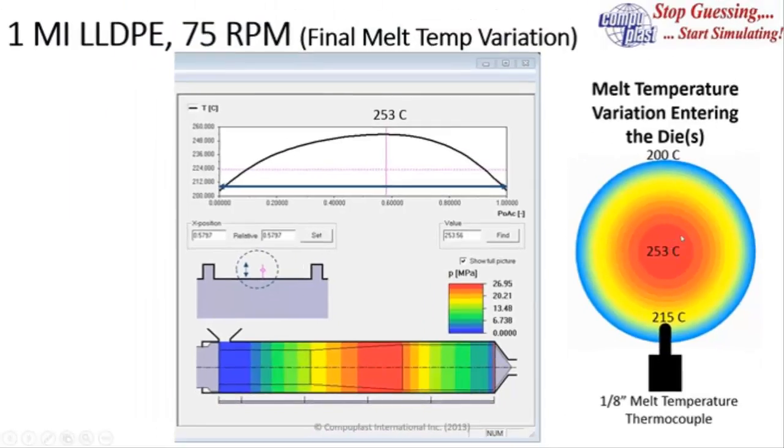The barrels are set at 200, let's say we hold our adapter wall at 200. And the melt temperature in the middle is scooting along at 250 degrees Celsius, and if we're fortunate enough to have a melt temperature thermocouple probe in there with a standard 1/8 inch immersion, we might be able to pick up in the gradient a temperature of 215 degrees C. And many processors are misled by this type of scenario, where they're measuring the temperature near the barrel wall, and they feel that their melt temperature is 215 degrees C and quite acceptable, when in fact, their temperature is actually much higher than that, because this is where the bulk of the material is flowing, and it's hitting at temperatures in excess of 250 degrees Celsius. So it's very important to have an optimized screw that gives you a very uniform melt temperature, because this is what's going into your dies and affecting your die distribution, all your die performance, the flow uniformity, all those things are affected by this temperature variation.